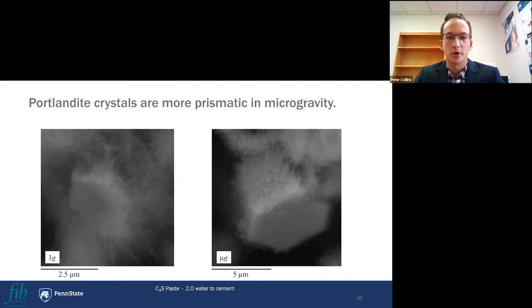And it's also important to note that the CSH doesn't grow as chaotically as it does in terrestrial gravity. You can see that there's some order to it, where it's growing at an angle up to the right or up to the left, and just kind of crisscrosses the whole way back.